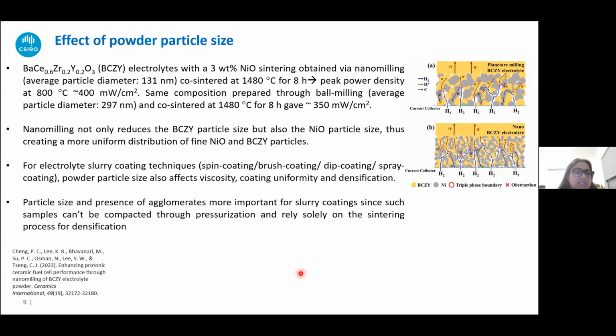So the thing is, the nanomilling, that is a higher rotational speed during the milling process, is not only reducing the BCZY particle size, but it is also helping in mixing whatever other sintering aid you have there, or maybe other catalyst particles you have there. So a more uniform distribution is being created, and that kind of uniform distribution also helps in the sintering process.